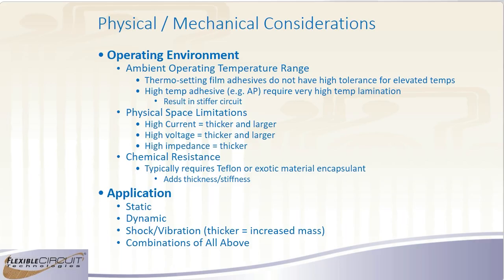Is there a way to calculate the minimum bend radius for strip lines, especially for strips that have very thick parallel copper layers? Good question. And this isn't just for strip line, it's basically any flex. It's basically a bend ratio. And if it's a strip line, it's going to be at least 3 layers, which makes it a multi-layer.